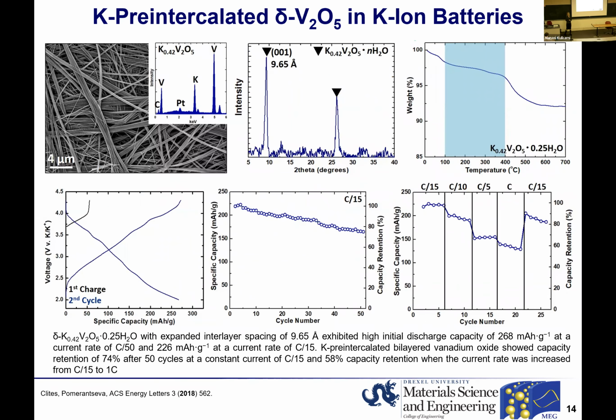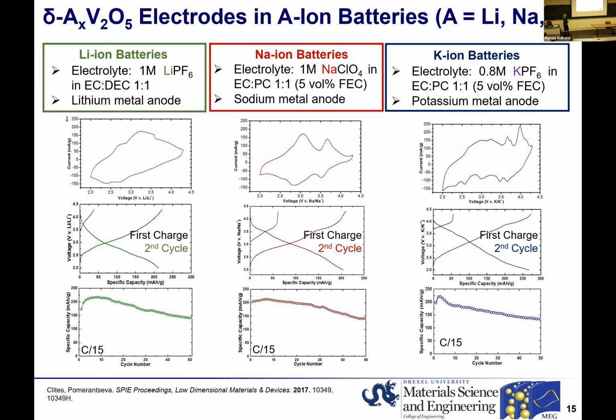And we selected potassium to show the same thing. So we chemically pre-intercalated potassium ions and cycled the resulting material in potassium ion cells. And what we observed is very high capacities for potassium, because this is a heavy and large ion, so usually its diffusion is hindered. But with chemical pre-intercalation, we see very nice capacity values, and also not bad rate performance, meaning that the material can withstand relatively high currents without losing much in its performance. So it confirms our suggestion that this synthesis leads to advances even beyond lithium-ion batteries.